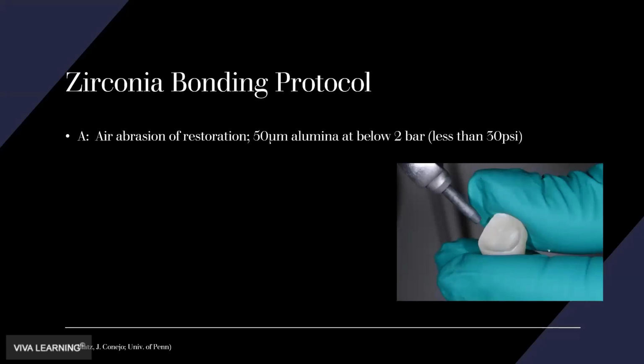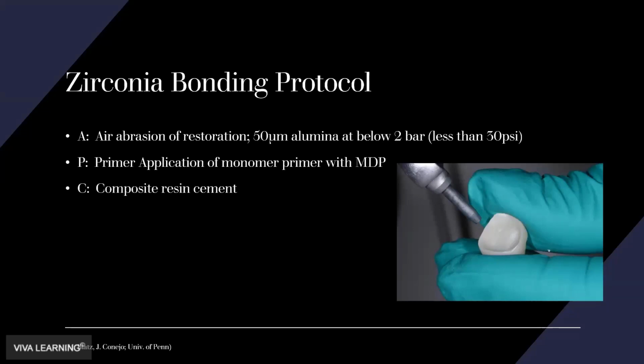You want to use air abrasion of the restoration with a 50 micron aluminum oxide at 2 bars or less than 30 PSI. And we then want to apply the monomer primer that has the MDP in it. And most of the ceramic primers that we have nowadays in almost all kits have an MDP in it. And then we add our composite resin cement, and then we deliver the restoration. So that's a simple zirconia bonding protocol for those of you out there that want to bond zirconia or have situations where you may need to bond your zirconia.